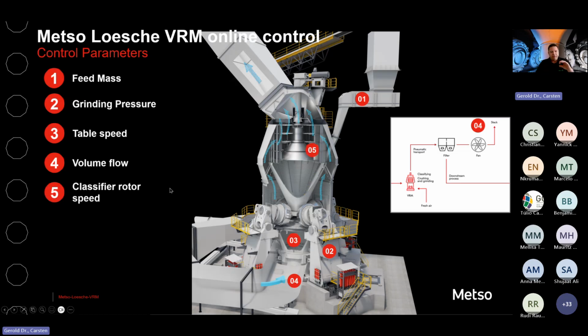You can basically follow your degree of mineral liberation, which you will never, or only with great difficulty, achieve with a wet milling system, because you have your ball charging and you're relatively limited in the range that you can set for your critical speeds. But in this technology, it's really very easy to change your final product or follow the degree of mineral liberation.